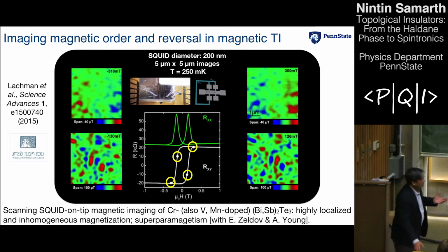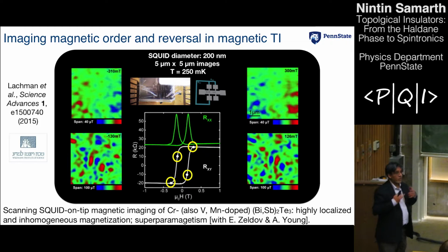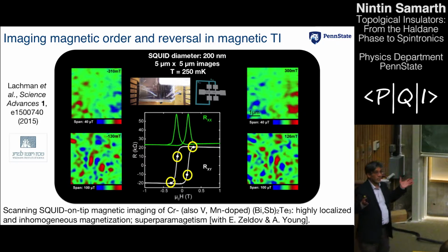And what it appears to be is that, when I told you that these samples, not just mine, but everyone else in the field who grows these materials, are highly defective, we believe that what's happening is that the magnetism is accompanying this magnetic disorder and this structural disorder, and the domains are strongly pinned. And so what we are seeing is strongly pinned magnetic domains that are constrained to switch locally without propagating domain walls across the sample. Okay?